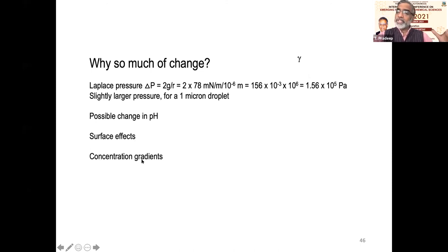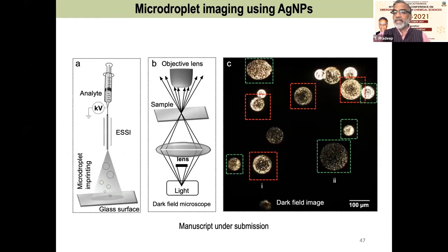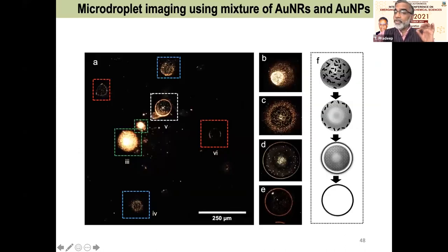So here is a nanoparticle suspension. You spray it. You collect this nanoparticle suspension. So you get droplets. These micro droplets contain nanoparticles. Now, using nanoparticles, you can image these droplets. And these are those particles there. So you see an image. Now, what you see in great detail is that there are many particles wherein a lot of particle concentration happens on the surfaces.